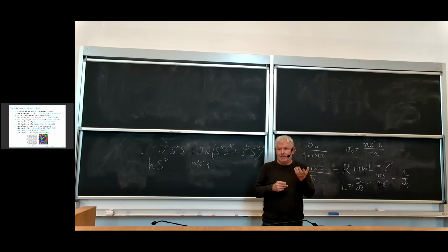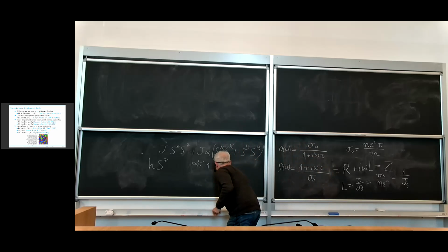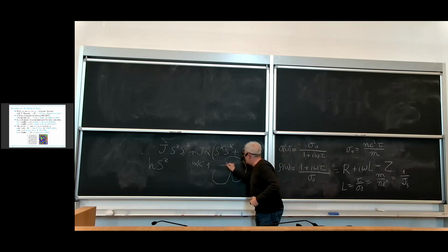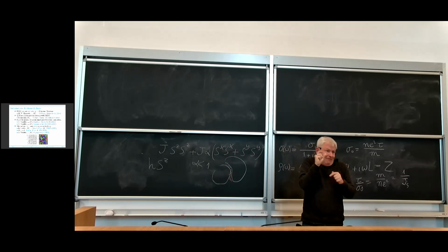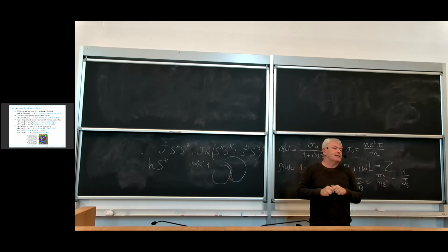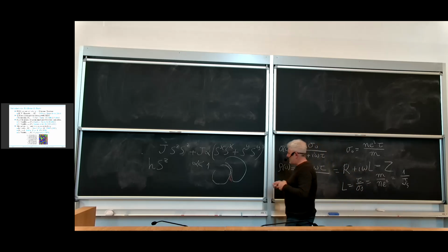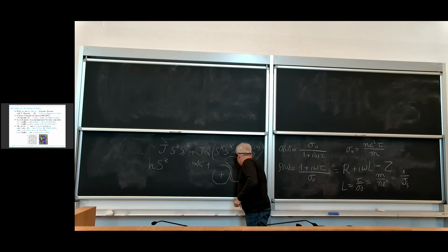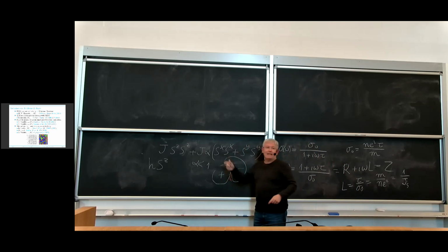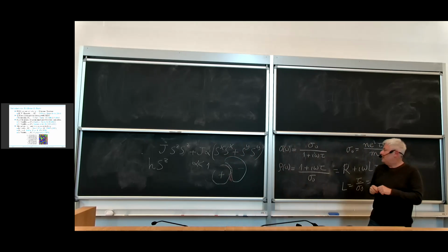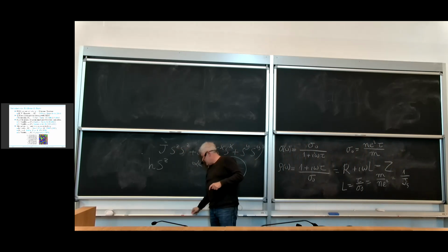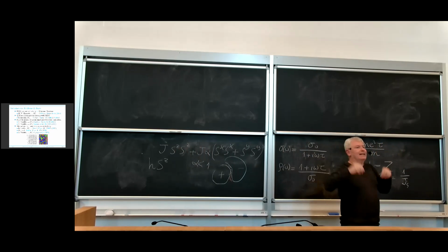What was surprising to us is not only that in going from a positive to a negative domain you have to have a region where your magnetization is in the plane, but that when we measured the superfluid density, it was finite. So the system is maybe not so strong, it's rather fragile, but nonetheless it's a filamentary superconductor. And this was really surprising. So when you go from plus to minus, this filament sneaks between two different domains of the Z spin polarization of your Ising-like model.